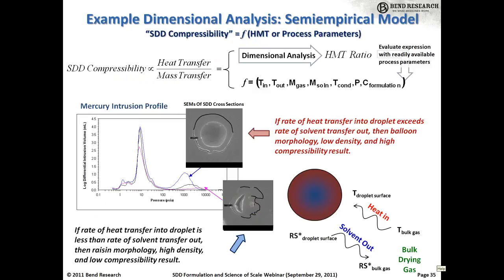So then, also bringing in the effect of thermodynamic process parameters on the SDD morphology. In the case of the recycled larger closed loop spray dryers, it's not as simple as just correlating to outlet temperature. So we developed this HMT ratio by performing a dimensional analysis on the heat transfer rate into a droplet over the mass transfer rate of solvent out of a droplet.